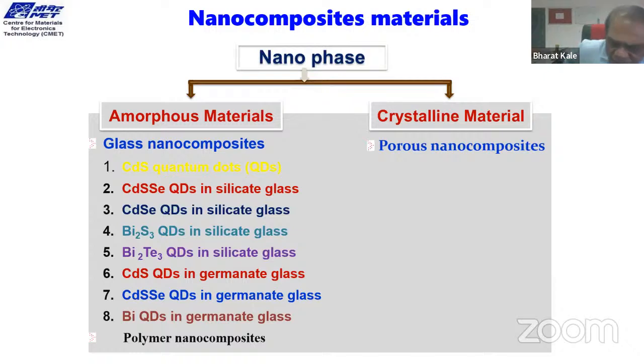But what we see now is that the stability of any quantum dots is very low. Suppose you have cadmium sulfide of 2.5 nanometer; after a week, if you measure the size, the size changes with time. There is accumulation of particles together, 1 nanometer, 2 nanometer together. They come together and form bigger particles day by day. Whether we can isolate them,